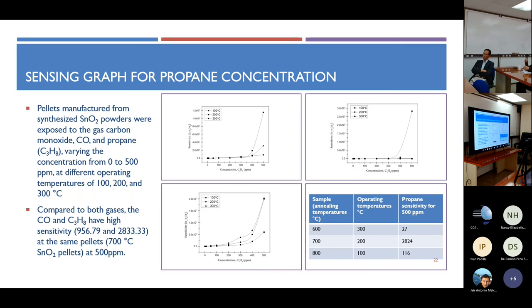And this is for propane, where 700 degrees Celsius also shows a higher sensitivity, while 600 and 800 are lower. It is exactly the same as CO: the sensitivity response versus the concentration in ppm at the three operating temperatures.